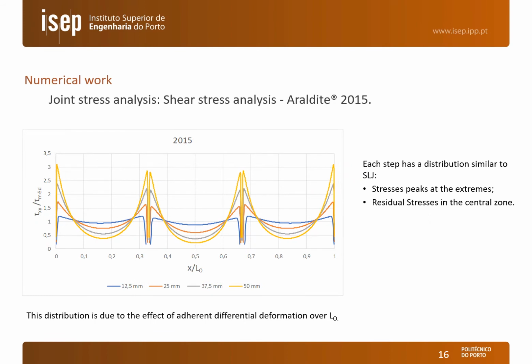Here we can see the same study, but now considering the shear stresses for the same adhesive. We can see clearly the different steps along the overlap length, and we have a similar behavior between steps. Within each step, we tend to have peaks at the step edges, and this is due to the shear lag effect that is widely known for single lap joints. And we can also see that as we increase the overlap length, we have increased peak stresses compared to the average shear stress in the joint.